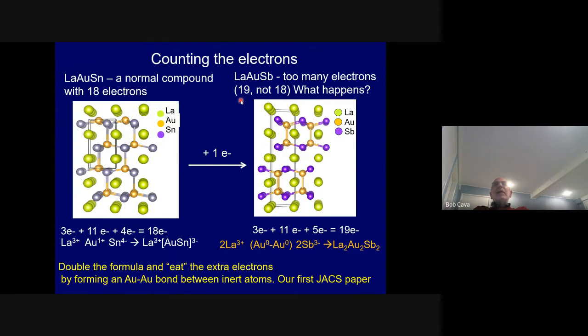Well, you do. And when you do, you get some bizarre event, which is that the layers shift relative to each other to put the golds next to each other. And when the golds get next to each other, the golds actually form a bond. So you get a gold-gold bond between gold zeros in this crystal structure. And you get what's called aurophilic bonding, which turns out to be making a bond between inert atoms, which is very bizarre in chemistry, and we finally got one.